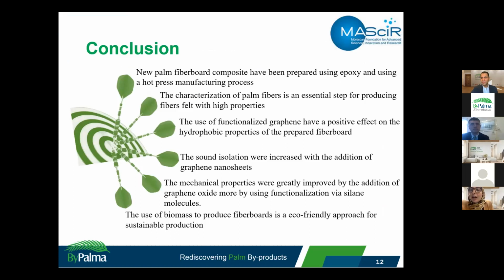Finally, it can be concluded that our fiberboard panel, based on modified palm fiber felt with functionalized graphene oxide, has been successfully produced using a hot press manufacturing process and epoxy resin binder. The soundproofing of our material has been enhanced with the incorporation of modified graphene oxide. However, the mechanical properties of our epoxy hybrid composites are very close to those of neat epoxy palm fiber felt composites. So enhancing the hydrophobicity of the fiberboard panel may be a great way to minimize the water swelling damage via decreasing the water droplets sticking on the surface due to the higher surface tension gained via the incorporation of modified graphene oxide in the panel.